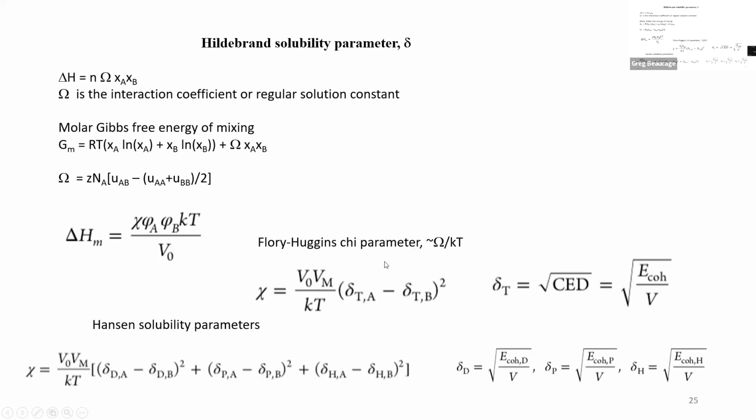But there's different kinds of oil, like aromatic and paraffinic oil. So you can calculate this del and just different kinds of rubber, like SBR and butyl rubber and this and that. So you can figure out what's going to mix with what. It turns out if this difference is less than something like 1, whatever the square root energy units, then the things will mix. If it's bigger than that, they kind of don't mix. There's a rule of thumb for that. So you can also use it to directly calculate the Hildebrand mixing parameter and predict the phase diagram if you want.